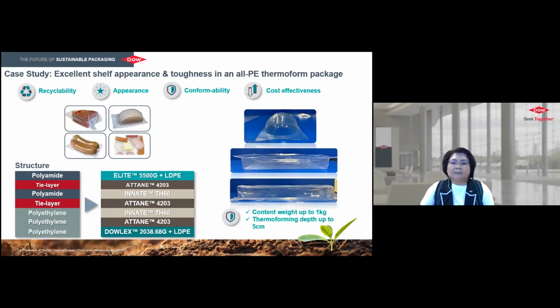A typical incumbent thermoforming films solution for packaging applications uses polyamide for thermoformability, which is related to stiffness and toughness, with the added advantage that shape retention after forming can be achieved. And with polyamide, the draw depth can also be deeper during the thermoforming process. However, as explained earlier, polyamide may not be the best material of choice when it comes to recyclability of such